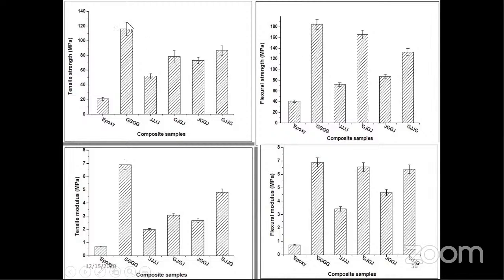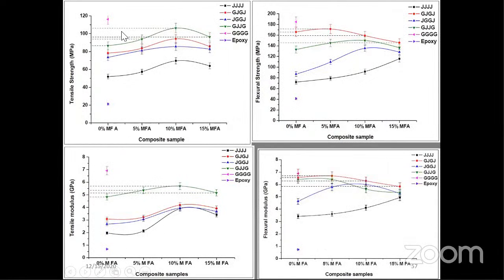So in all the results, the glass fiber composites are showing better results. So the next technique we went on with is micro particles along with these hybrid composites. Along with the hybrid composites, we added some nano fillers and micro fillers to see whether there is a chance of increasing the strengths or not. Still none of the materials are capable of replacing the conventional glass fibers straight away.